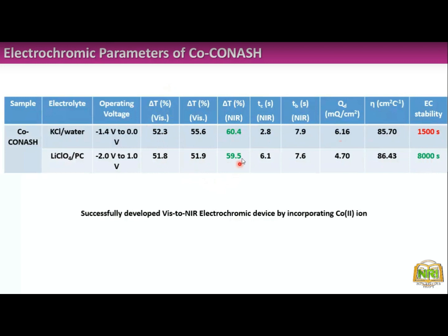And compared to the previous devices, the switching time here is a little high. This is only because propylene carbonate is viscous in nature, so the counter ion diffusion, of the lithium ion or perchlorate ion I showed you, and the electron transfer become a little less. The counter ion diffusion is a little less because of the viscous nature. That's why it takes quite a long time to change the color. But compared to other reports, where a lot of materials have been reported, it is completely moderate.